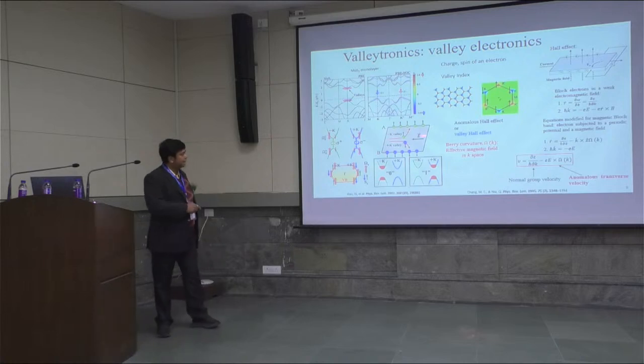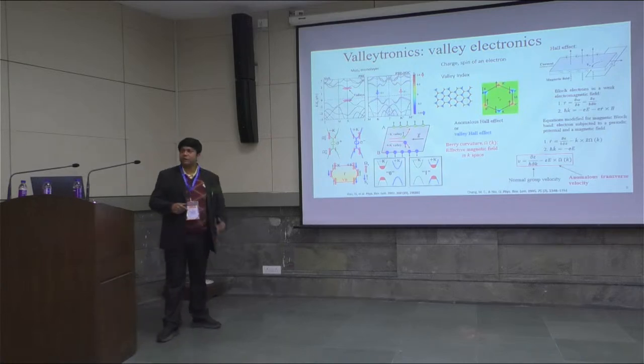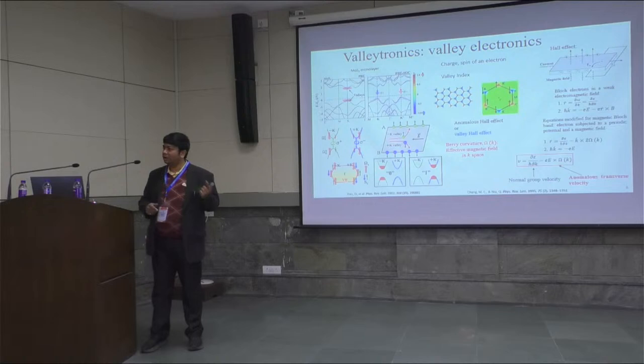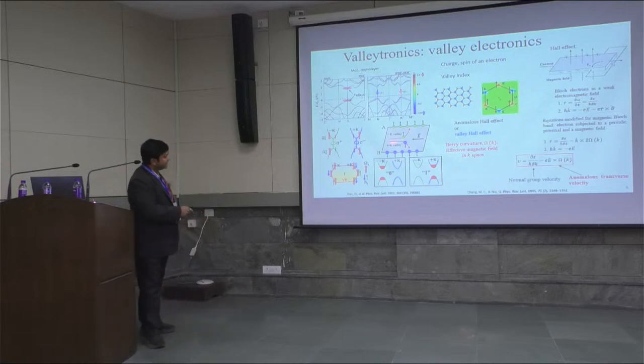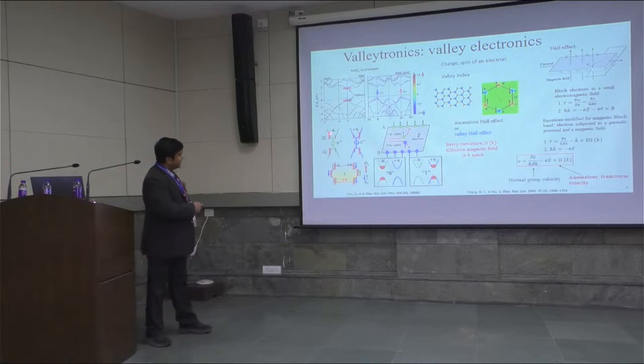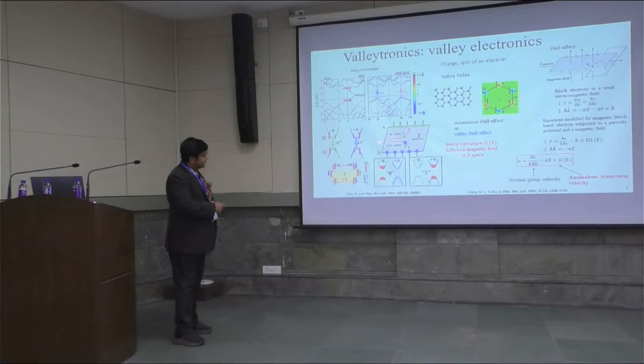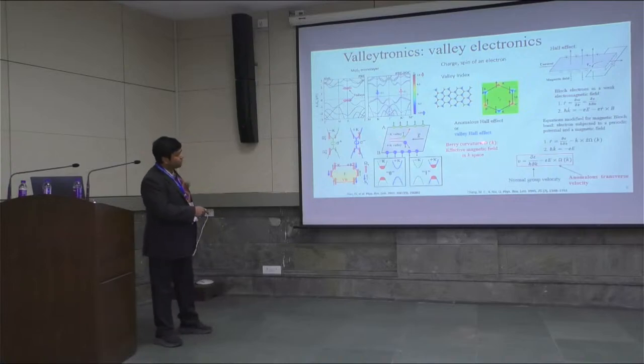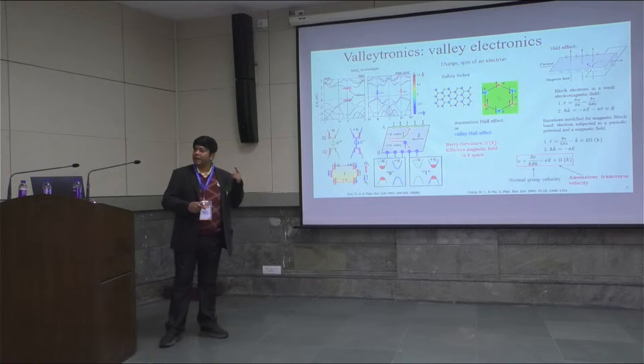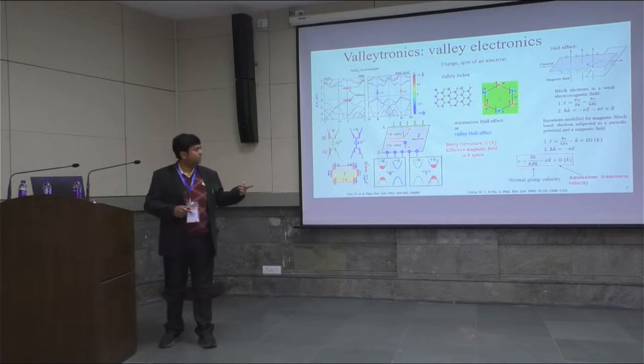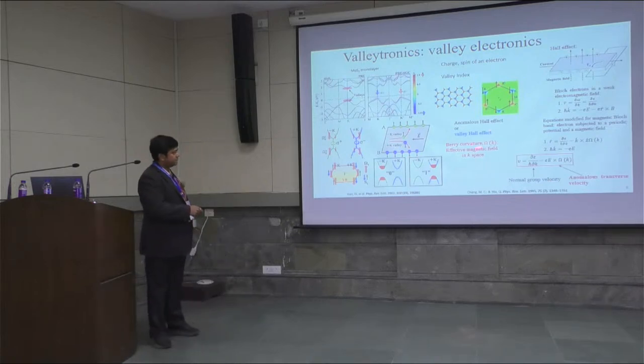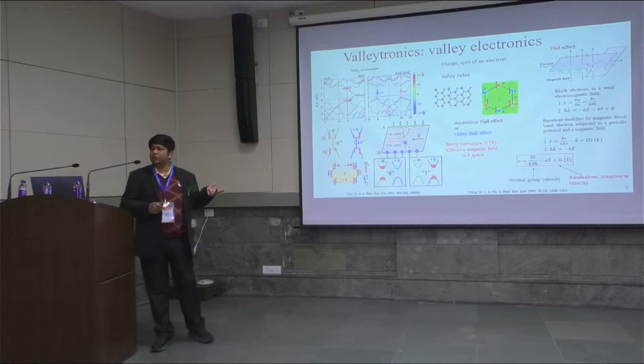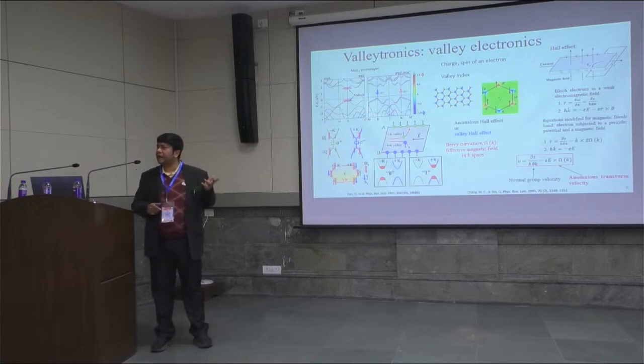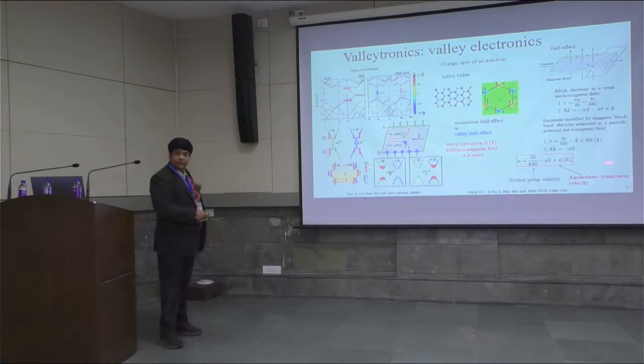Then, like in the Hall effect, when experimentally you study the Hall effect, you need to turn on the electric field. And then the carriers in this valley experience an effective magnetic field in K space, which is due to an intrinsic property of the material having a broken inversion symmetry and spin orbit coupling. So that is the Berry curvature. And the higher the spin orbit coupling, usually the higher is the Berry curvature and the higher the valley polarization. So this is a v cross B kind of a term here.